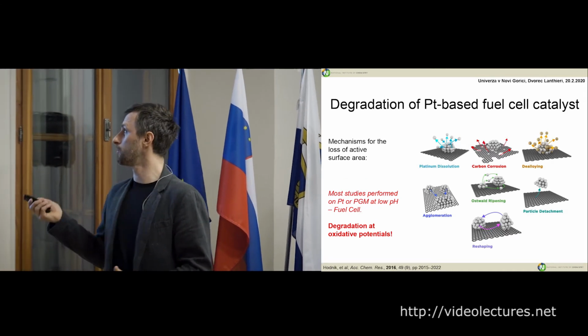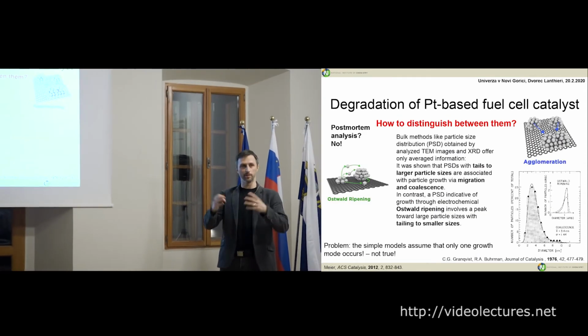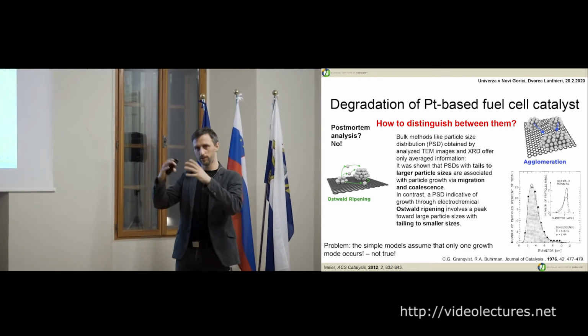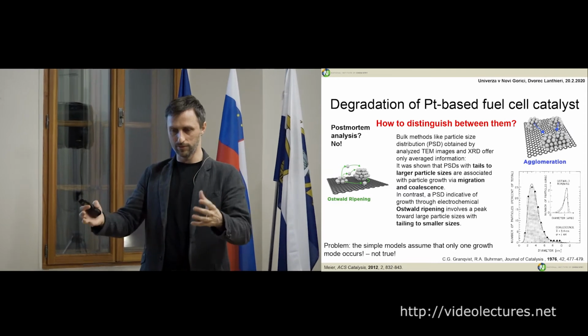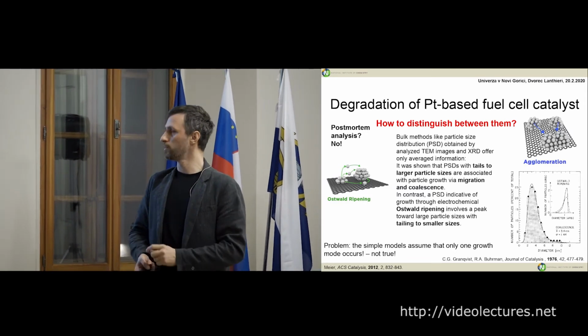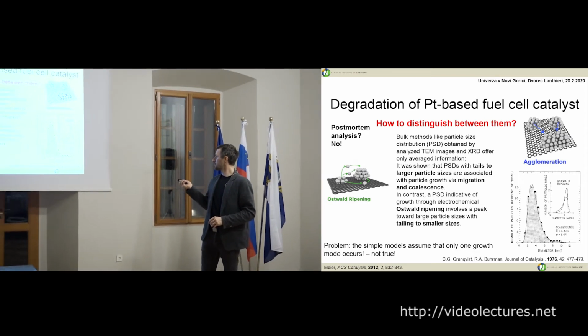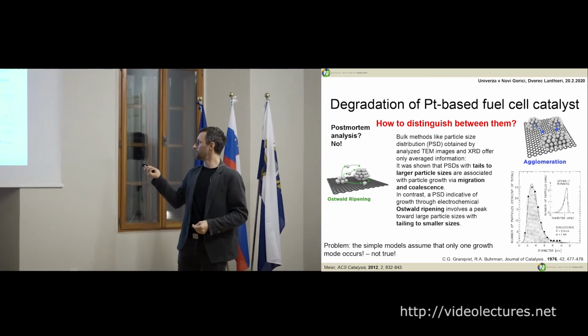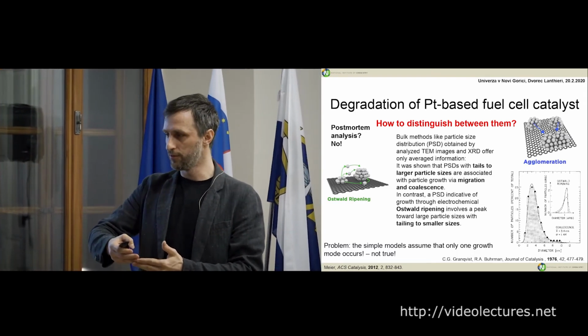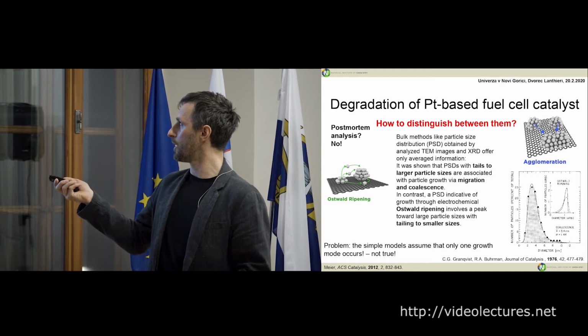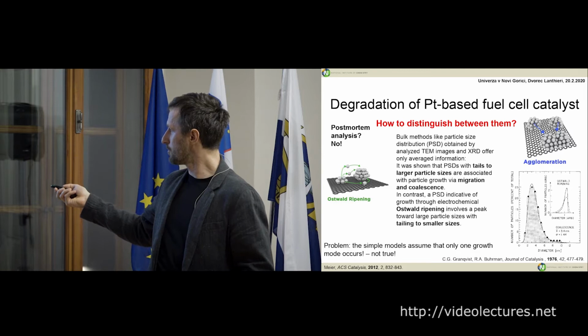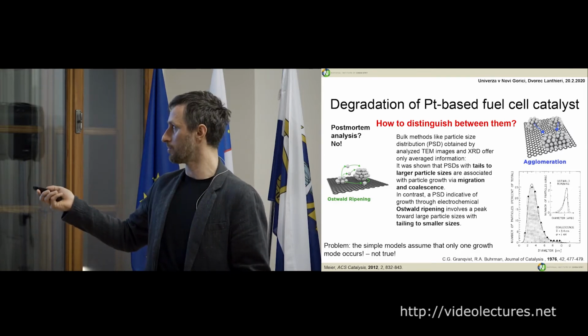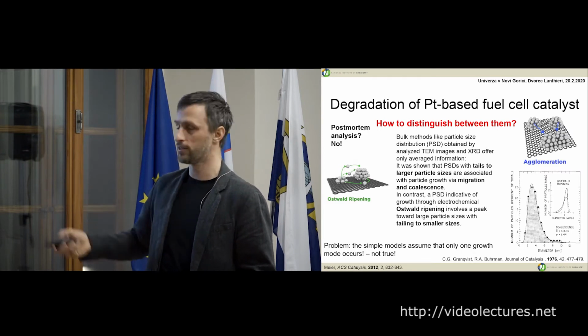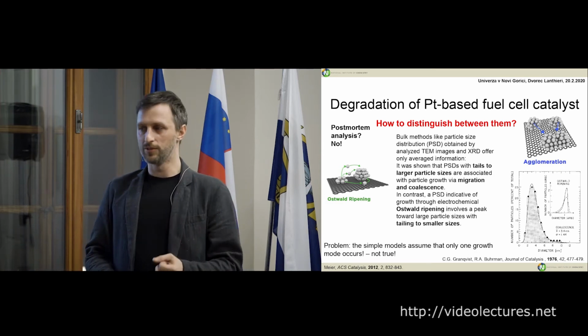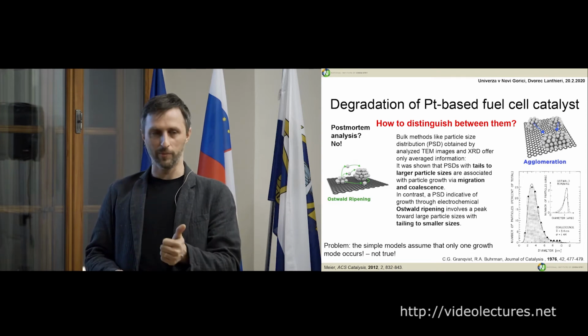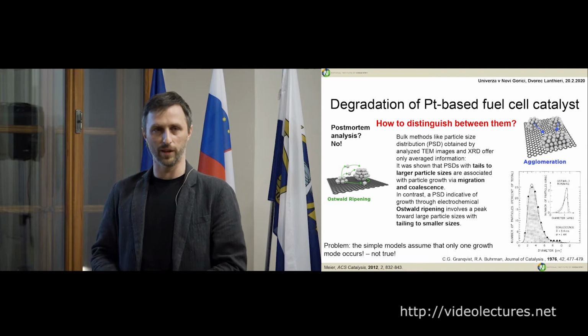Now, the question is how to distinguish between these two mechanisms, because they both result in bigger particles. Ostwald ripening is dissolution of small ones onto the bigger ones, and this one is coalescence, and then you get big particles. There's an old way to do it: you do the particle size distribution. You can do this with different techniques, with XRD also. If you examine this and you see tails to larger particles, because you have more larger particles, you can say this is coalescence or agglomeration. But if you have tails to the smaller particles, it should be Ostwald ripening. Now, this is maybe good if just one mechanism is happening and you don't have any information on what's happening with individual particles. So it's quite broad and general.